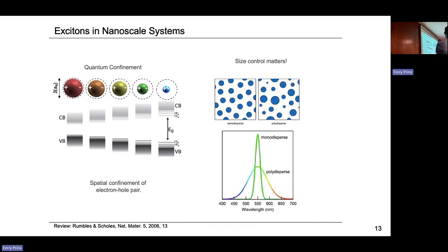So, size polydispersity—if you have a very monodisperse ensemble, where all your synthesized nanoparticles have the same size, then you're going to get a very nicely well-defined absorption spectrum and a very nicely defined emission spectrum. If you don't control it so well, you're going to get a smeared out absorption spectrum, because the smaller particles of your ensemble are going to have a bigger band gap and the bigger particles are going to have a smaller band gap. So polydispersity at the end will result in your spectral features being less defined.